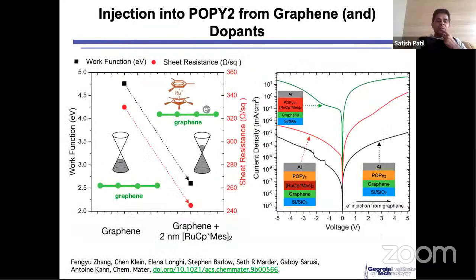Okay. So, Seth, I have a question. In the last couple of slides, you have been talking about changing the work function of the electrode by introducing these dopants. And we have this thin layer of a dopant. On top of that, when you deposit the active layer, there will be a diffusion. In addition to changing the work function, do these dopants also dope the active layer? The answer is not really.